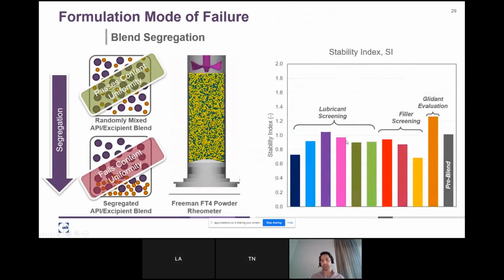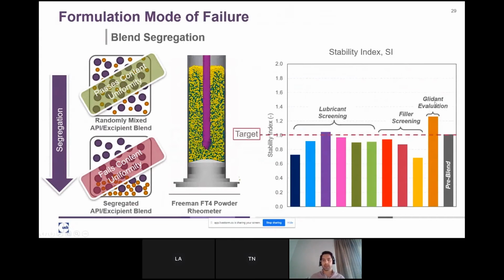So here's, for example, one of the examples from a formulation. We have different phases. We have lubricants in the formulation, different types of lubricants, fillers, and glidants. And here's our target. Once we have this stability value of 1, that means we have a fully stable formulation. You can see that as we change the components, of course, we get different levels of stability. So we have to choose the best one for the process.